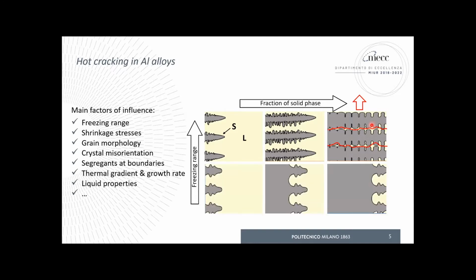One of them could be to decrease the so-called freezing range, the temperature interval of solidification, so that there will be a much shorter interval in terms of time and in terms of temperature gap along which the critical condition is set, so that cracks have a much lower chance to grow.